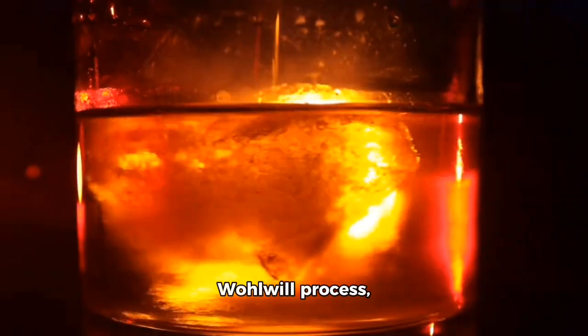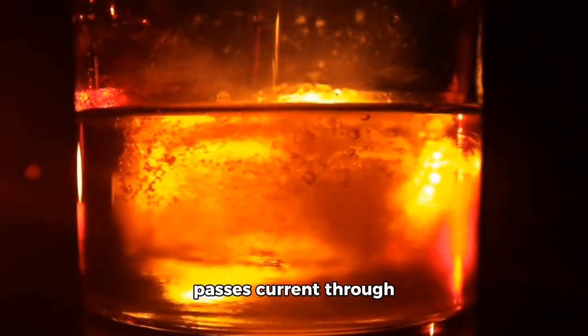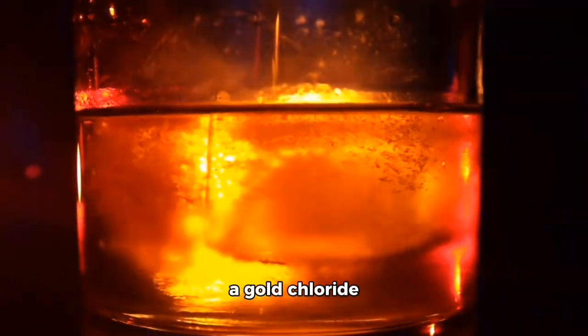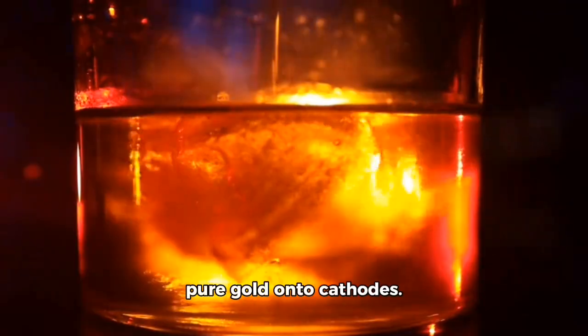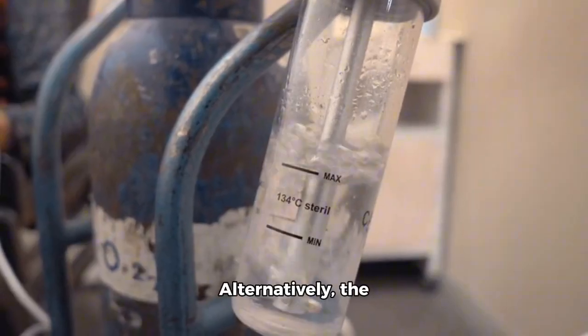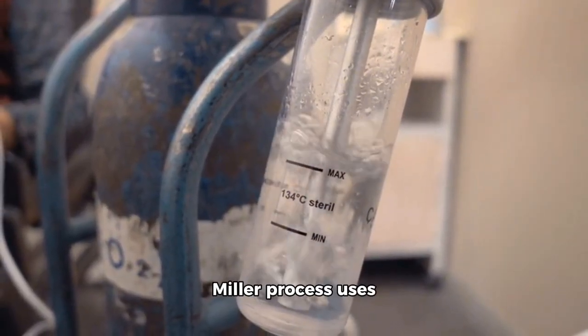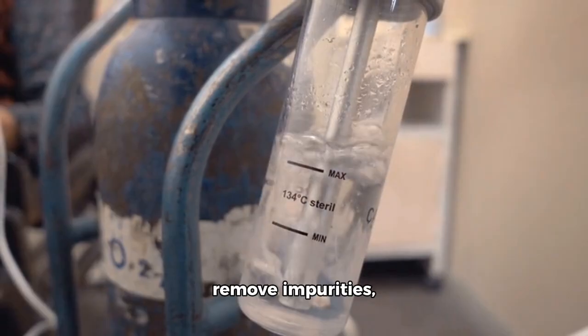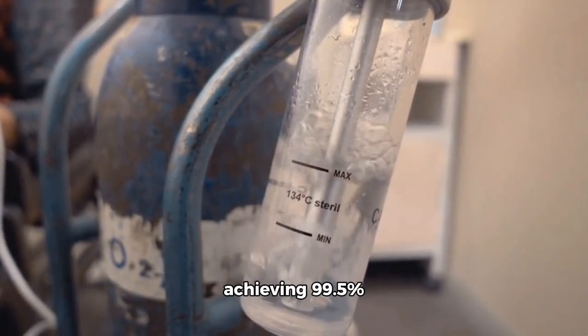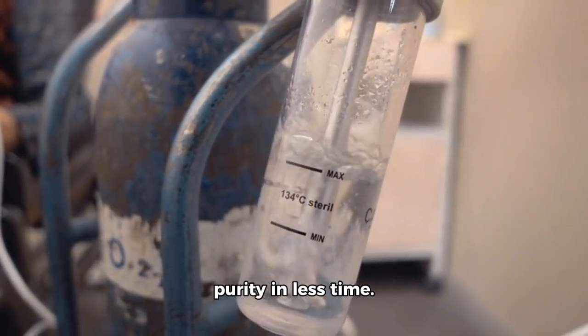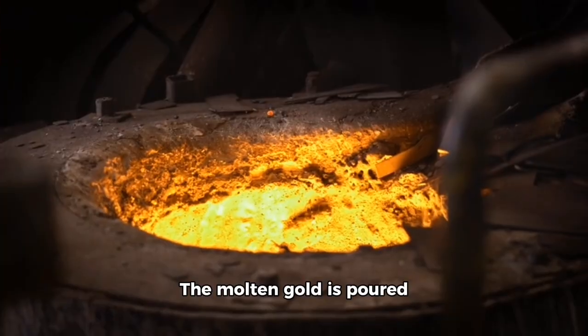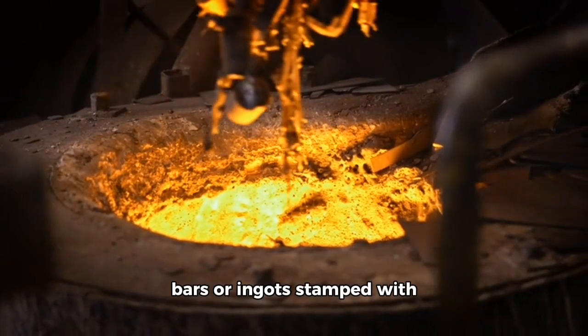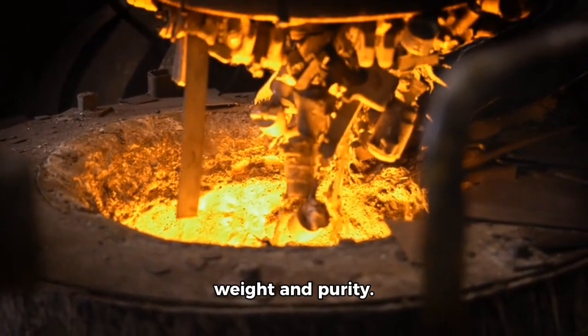Electrolysis using the Wohlwill process passes current through a gold chloride solution, depositing pure gold onto cathodes. Alternatively, the Miller process uses chlorine gas to remove impurities, achieving 99.5% purity in less time. The molten gold is poured into molds, cooling into bars or ingots stamped with weight and purity.